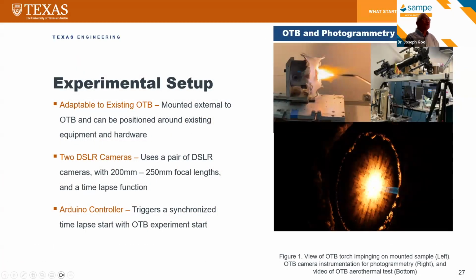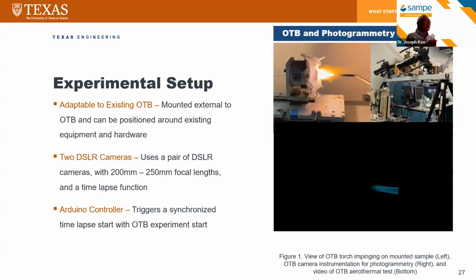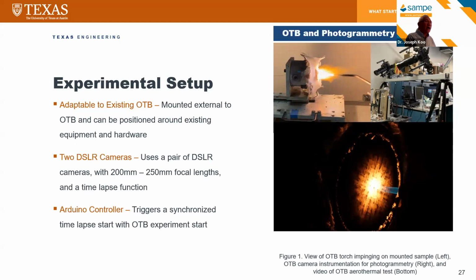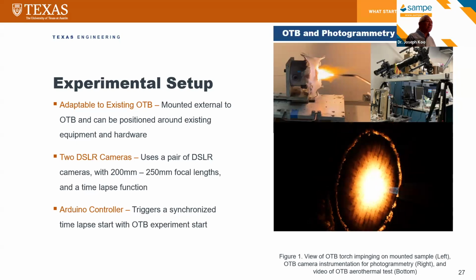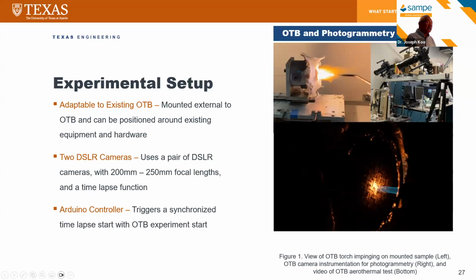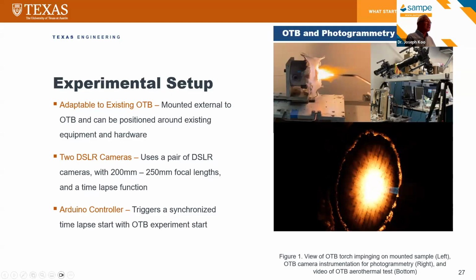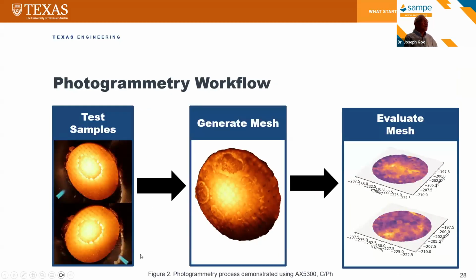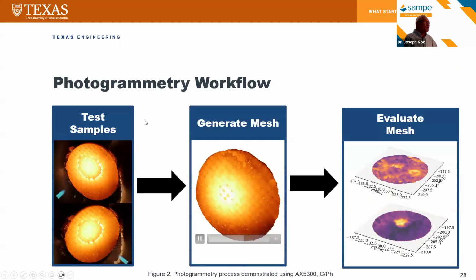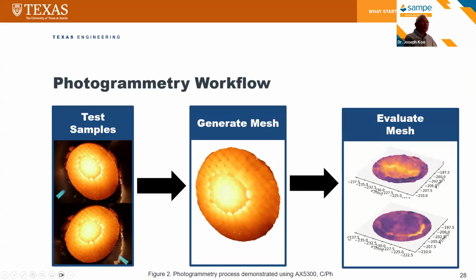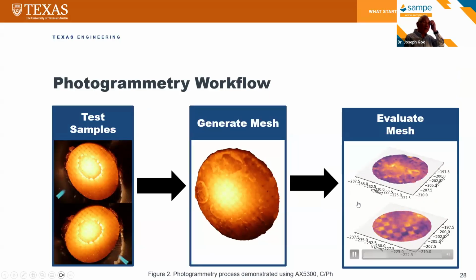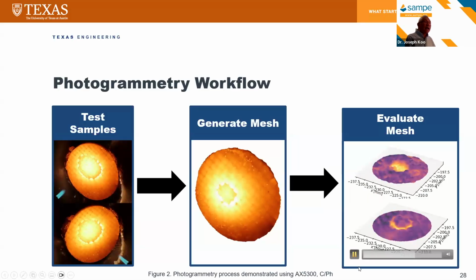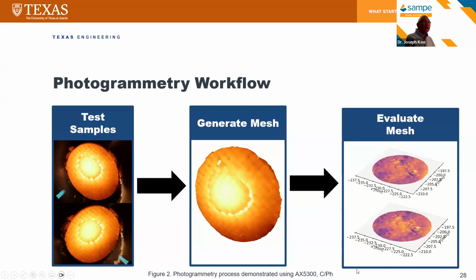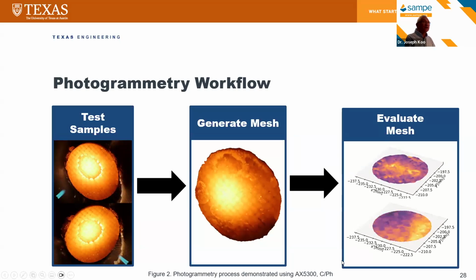Okay. So this is something that we started developing. It's called photogrammetry. Photogrammetry is a technique where you use two cameras and you are able to map the in situ recession during the testing. This is what we call a workflow. We have the test samples and we generate a mesh, and we use the two cameras and the in situ data we are collecting. And this is what you could see, that we are able to calculate the in situ recession rate of these materials we tested in our lab.